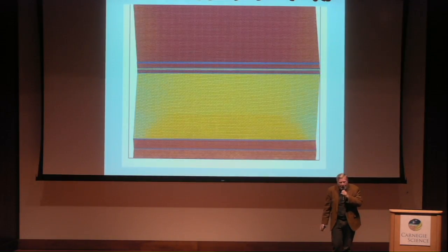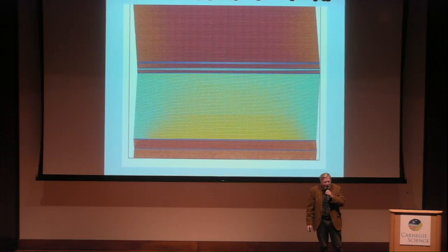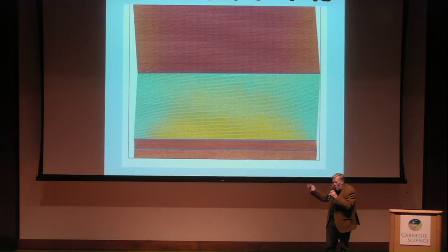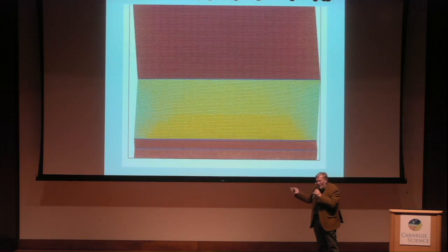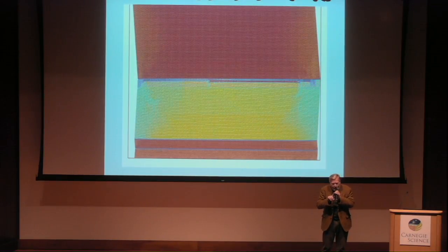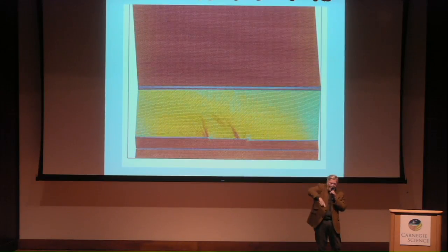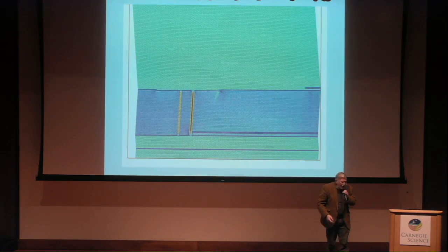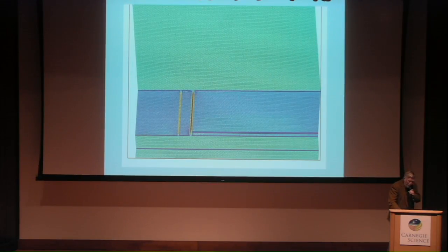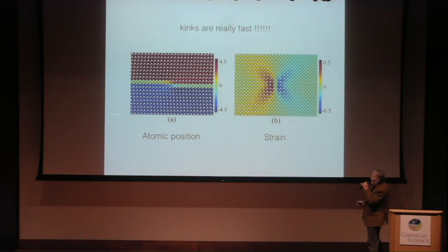And of course, if you remember Mach cones, that's a Mach cone. So these guys, just from inspecting optically, you can see they're already supersonic. They're going so fast that the forward beam in the phonon is folded backwards, and you can see it in the backwards direction. So now you can measure or determine the exact form. So here again is the kink. This one is the Eshelby strain matrix. So that's this. It's a cross basically.